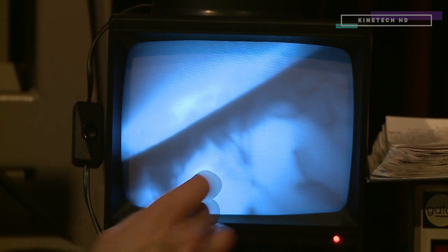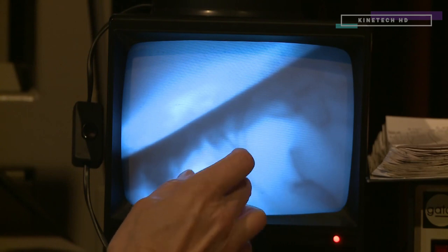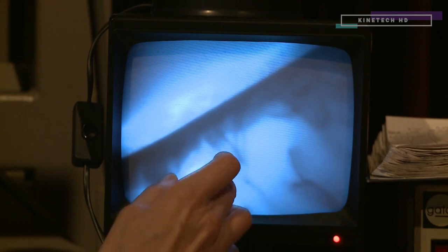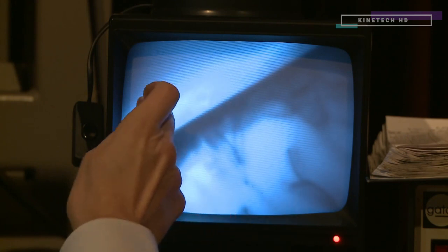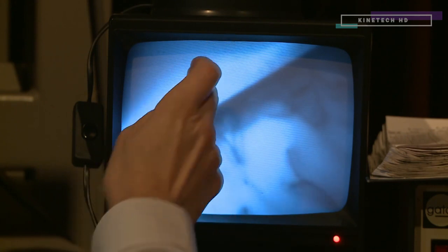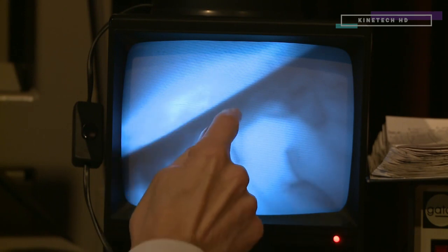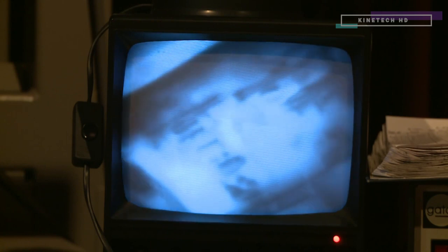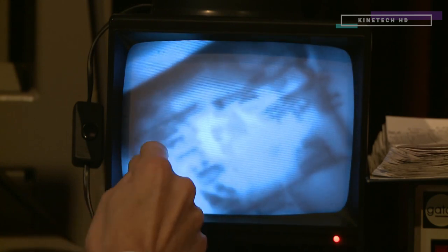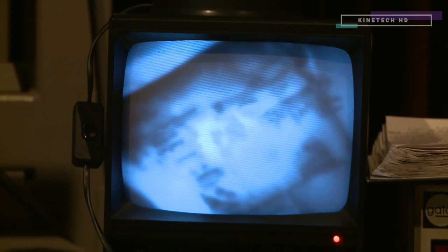What we're looking at here is a piece of LED which has been put into the electron microscope. The LED is gallium nitride, and this particular LED is in fact grown on sapphire, like any commercial LED you buy. This is the sapphire down here — and of course sapphire is quite expensive. This is the gallium nitride we've grown on sapphire, and these lines are the dislocations — defects in the crystal structure.